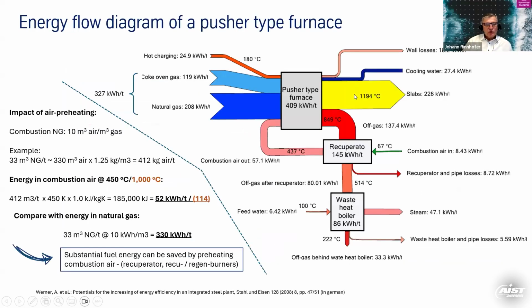And here we are. So when we look at the slab at around 1200 degrees, this is the yellow arrow here, we find again our 220 kilowatt hours per ton. This is the energy content of the slab. And we see all the losses around. We see especially the off-gas or flue gas loss, which is very high. This is the red area here. This is why we use this high energy to preheat the air again. This is the typical Sankey diagram of a reheating furnace.